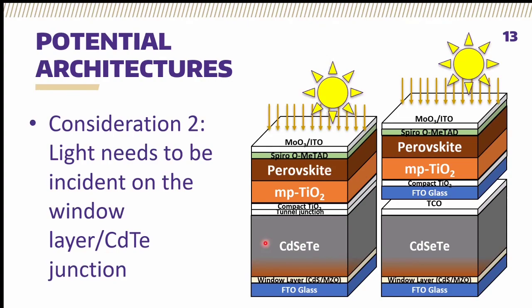Further complicating things is that the CdTe is not a traditional p-n junction. And unlike p-n junctions in textbooks, the optical depth of the CdTe and its junction layer are not the same. And so therefore you need photovoltaic light to be incident on this junction first. If you shine light from the top of the CdTe cell, from the opposite side of the junction, what happens is that light that's traveling through, that's supposed to be absorbed by the cadmium telluride, gets absorbed in this Schottky junction region of the device right here, leaving almost no photon flux at this back interface, where flux is tremendously important. Because there is no light here, the depletion region does not set up in this device as it normally should be, or as it normally does, meaning you have very inefficient CdTe devices that can't actually be used.